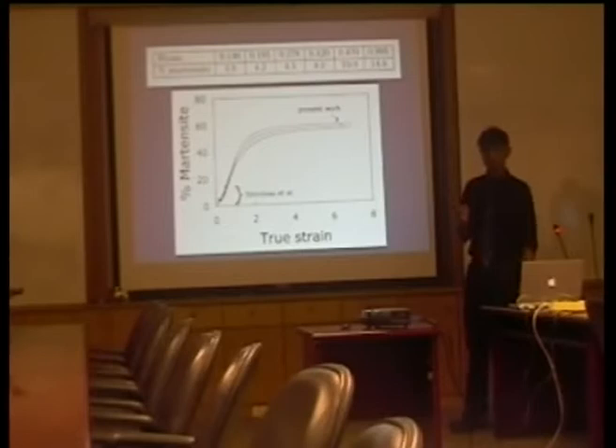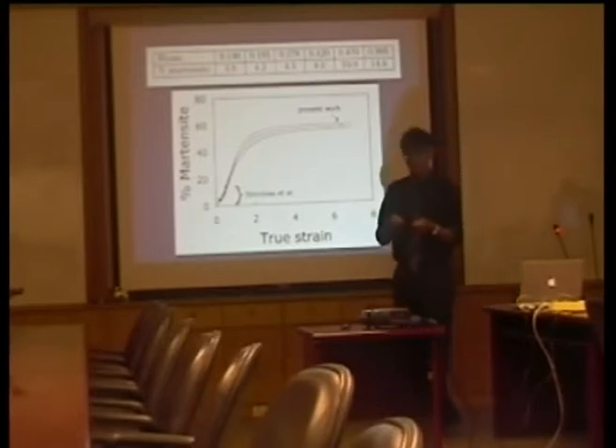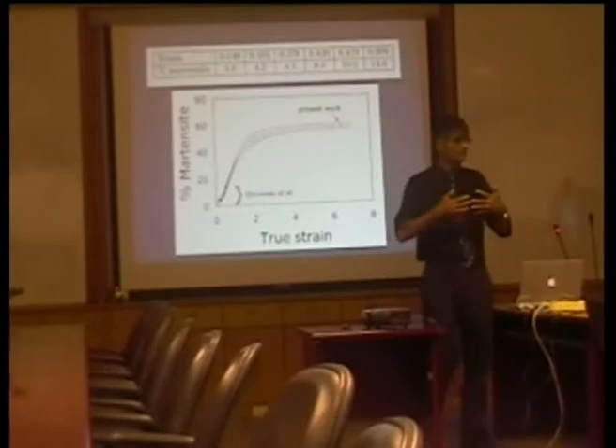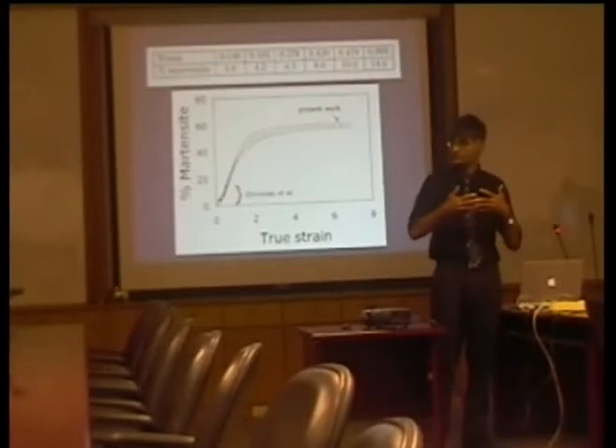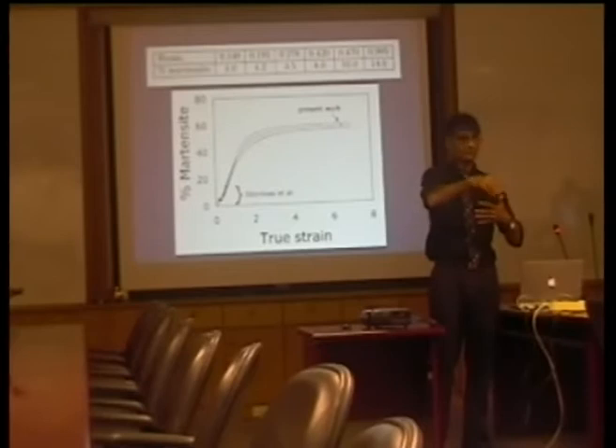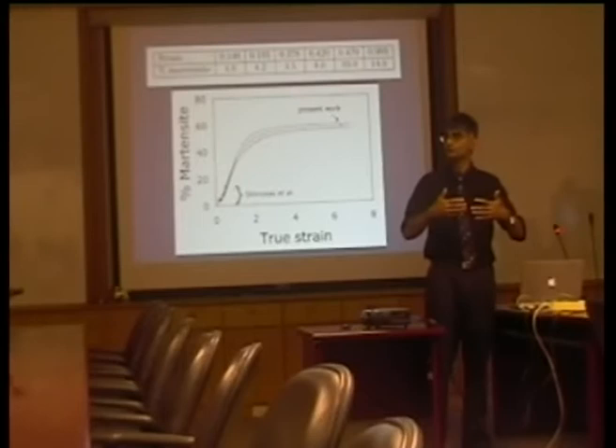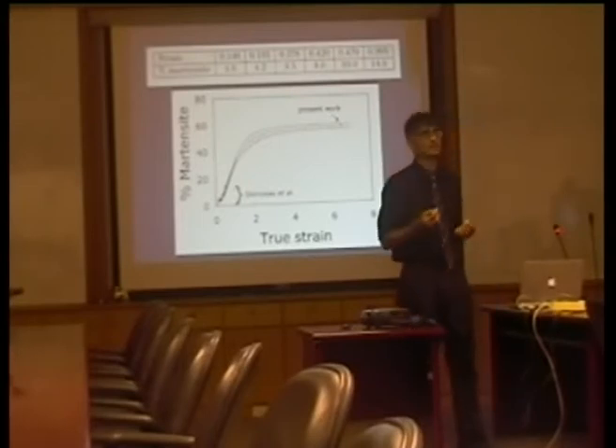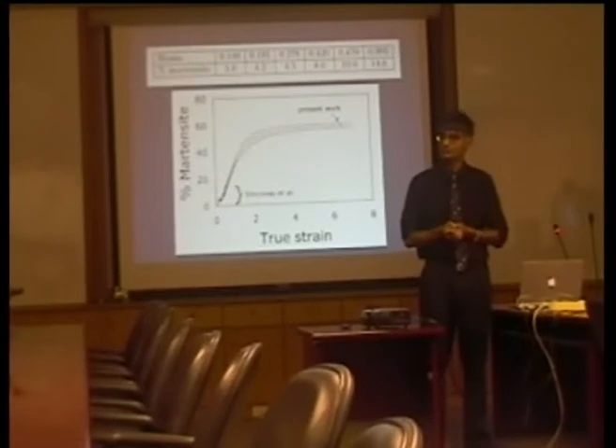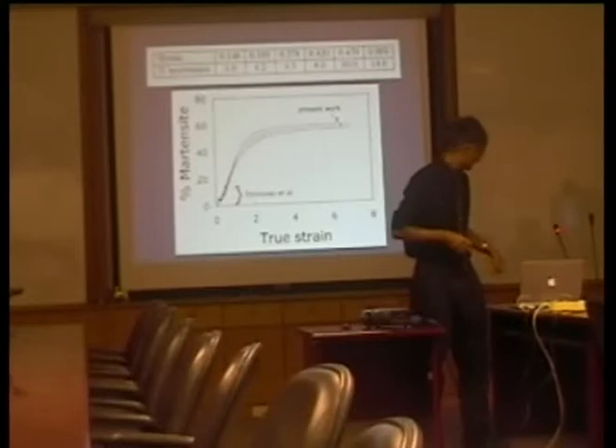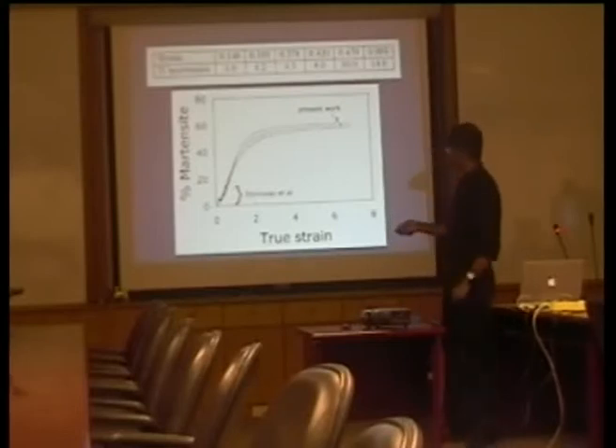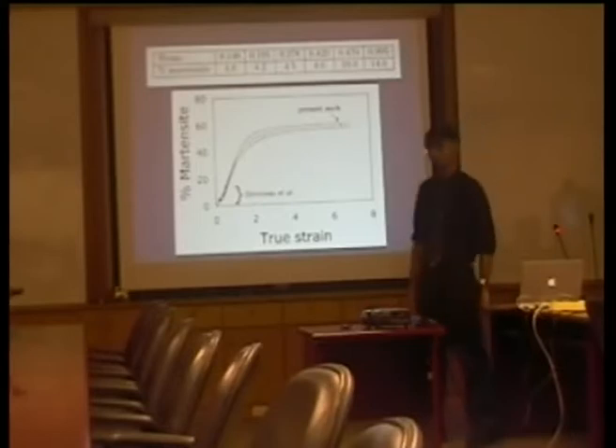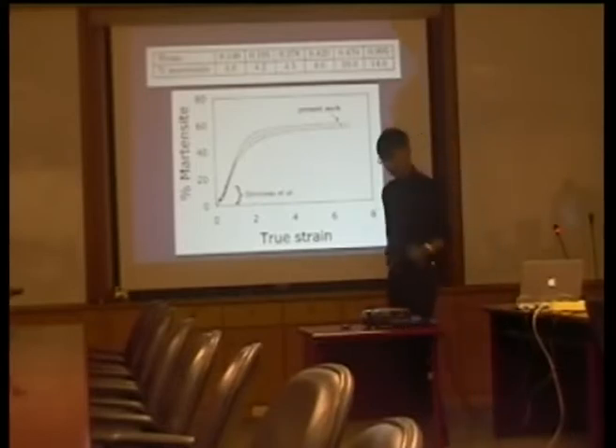And there's a further contradiction, that martensite is a displacive transformation. That means that the interface is a coherent interface with the austenite. If you put obstacles in the way of the coherent interface, then it will no longer move. So there is a well-known phenomenon known as mechanical stabilization, in which if you deform the austenite, then you retard the martensitic transformation. These results are inconsistent with that. Here we have an acceleration of the transformation as we increase the strain. So there are two contradictions.